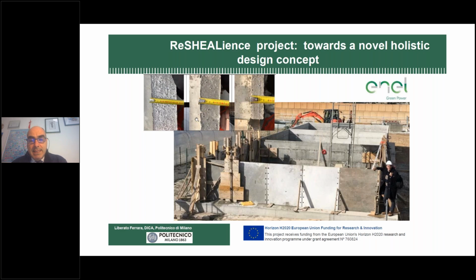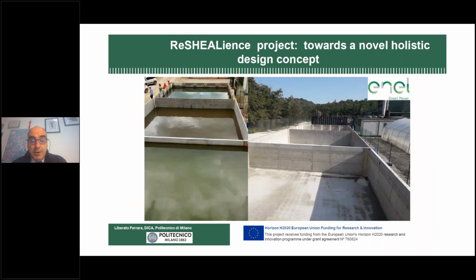We designed this basin with 3 different technologies. We have ordinary reinforced concrete, 10 centimeters thickness. We have cast-in-place ultra high durability concrete, 6 centimeters thickness, and we employed a partially precast solution. You can see this during the construction. This was February 2020. The slabs were precast with holes and the cast-in-place columns in between them. The material also filled the holes and realized the connection. But in this case, the slabs were only 3 centimeters thick. So we have a 70% saving on the material.